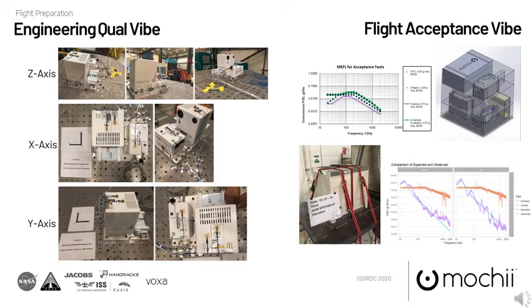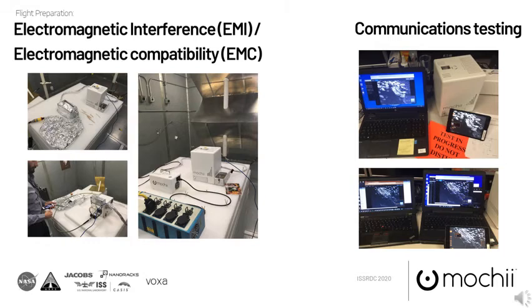The measurements from the test closely matched the predictions from the simulator, as can be seen in the bottom right-hand curve for one vibe axis, showing that the target attenuation was reached. This test was successful, indicating that Mochii had a high probability of surviving the flight under these packaging and nominal vibration conditions. With numerous equipment on station and broadcasting satellites on orbit, there are many opportunities for interaction and interference.